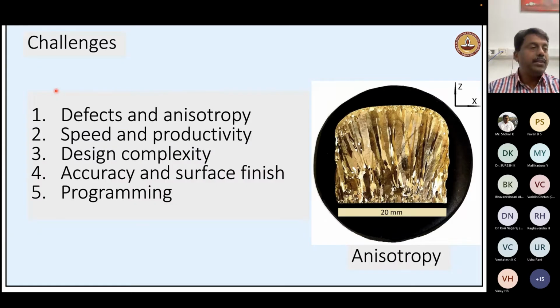Okay, so having said all of that, we're almost approaching an hour. There are challenges in additive manufacturing. The biggest challenge is defect formation, because as I said, if you use metals and alloys in DED or laser powder bed, it is a multi-pass weld. So whatever defects you may expect during welding, you may also see here, like porosity and lack of fusion. All these things you need to control.